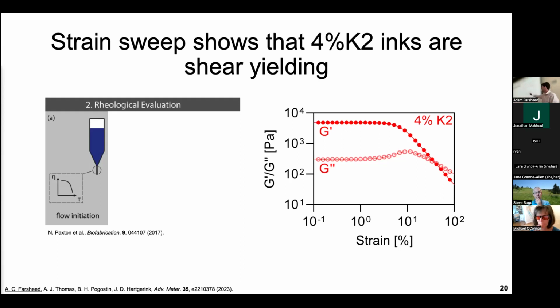And so what we're showing here on the right side is we're increasing the strain, so the amount that we're deforming our material. And at the beginning of the graph, we're seeing the G prime and the G double prime. And the G prime is over 10 times the G double prime, showing that we have a nice gel material. But as we increase the strain from left to right, we get this behavior where the G double prime actually will jump ahead of the G prime, and we get the transition from a gel to a liquid.